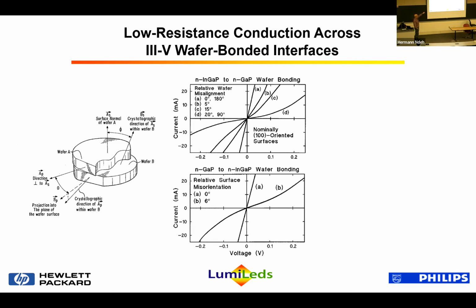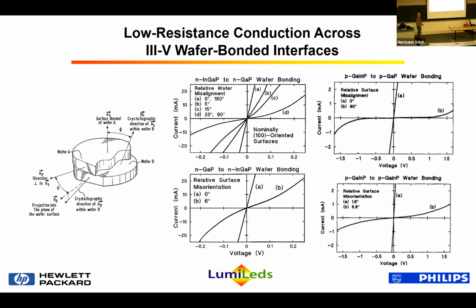And so we went from nice linear ohmic conduction to one that looked like there was a barrier at the interface. Similarly, when we looked at different surface misorientations, if we matched the surface misorientation or if we varied them by 6 degrees, we would see very different current conduction. So it's really important to align the crystal, even if it's lattice mismatched, across that interface. And we found that to be true of N-type. We also found it to be true of P-type. We found it to be true of indium phosphide, gallium arsenide. So this was one of the early learnings relative to what was important for wafer bonding.